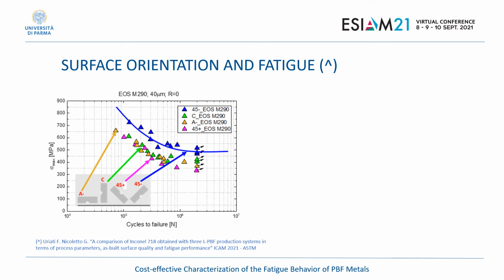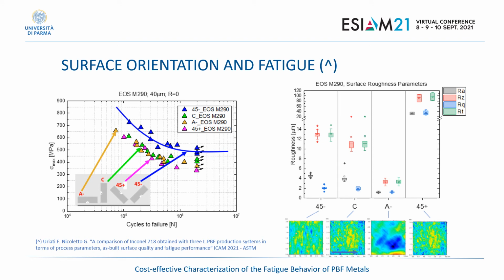The behavior that we see here in fatigue has also been investigated in terms of the original surface quality. Here on the right side, on the top diagram, we see the different surface roughness parameters measured for the different inclined surfaces. We can see that the roughness changes significantly depending on the orientation, as expected. On the bottom, we see also views of the surface morphology as obtained by an optical profilometer.